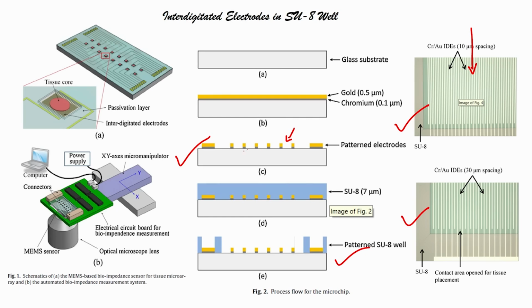Now, on this section C, that is a glass with interdigitated electrodes, right, patterned electrodes, we spin coat SU8. You can see here we have spin coated SU8. On this spin coated SU8, what will we do? We will pre-bake it, then we will load the mask, we will expose the SU8, right, and then we will do post baking, then we will develop, and then when we develop we get this particular wafer, this particular glass with interdigital electrode in the SU8 well.